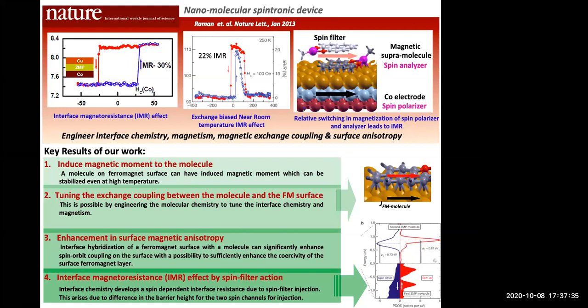Okay. And is it possible, do they self-assemble? Yeah, self-assembly is possible on inert surfaces very easily. They self-assemble easily on gold, platinum, inert surfaces. Because there the molecular interaction is dominant over the molecule-surface interaction. Okay. So when the molecular interaction is dominant, they self-assemble. I see. But if you have the first layer covered, then you can't keep on self-assembling even on, let's say, copper or iron? No, on copper also they self-assemble, and gold; iron is difficult.